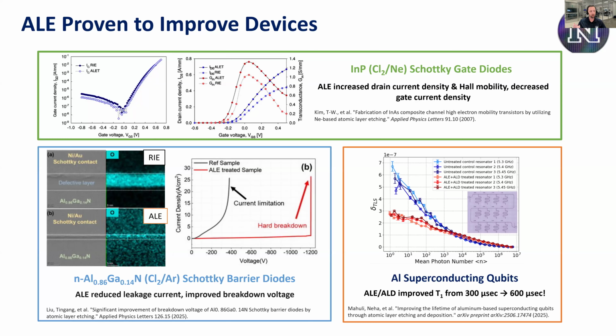At a high level, I just have my surface. As a surface scientist, I always like to point out that actually the surface is the hardest part to remove in anything because, of course, when we cleave any material, the material relaxes back, right? You get back bonding or oxidation or other effects going on where that surface is trying to stabilize itself. So we have to weaken that surface somehow. Interestingly, if you look into catalysis type work, the second layer tends to be a little weaker, and there's this kind of accordion-like sequence of bond lengths as you get into the bulk that eventually evens out. Anyways, so you dose this thing, you do some kind of modification. Maybe it's chlorine. The most common process, kind of the canonical ALE process, is chlorine, argon for silicon.